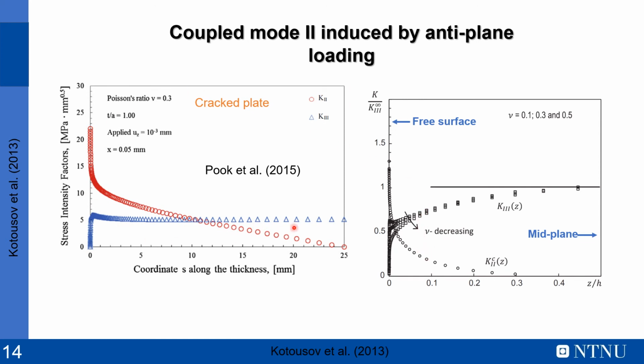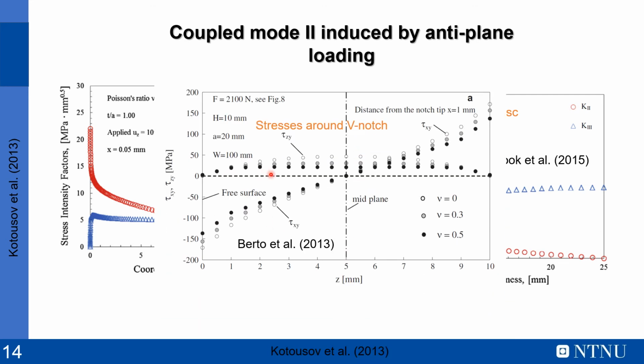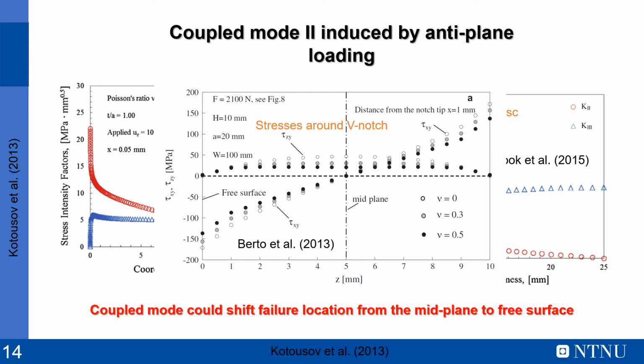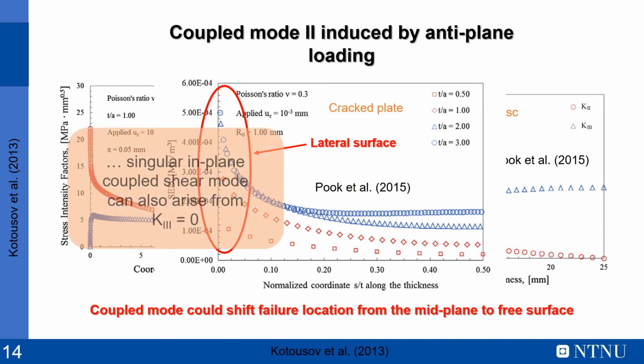A lot of works have confirmed these behaviors for the stress intensity factors and for the stress components, and therefore the coupled mode could shift the failure location from the midplane to the free surfaces. This could be assessed by using, for example, the averaged strain energy density, which in the case of Berto et al. has been used and confirmed that the failure location shifts from the midplane to the free surface.